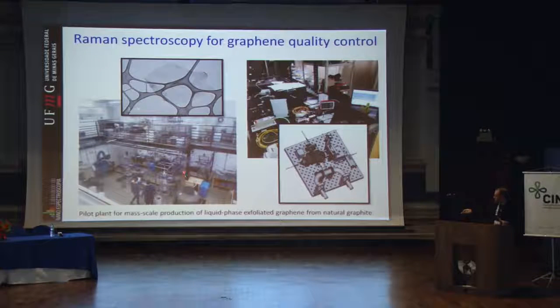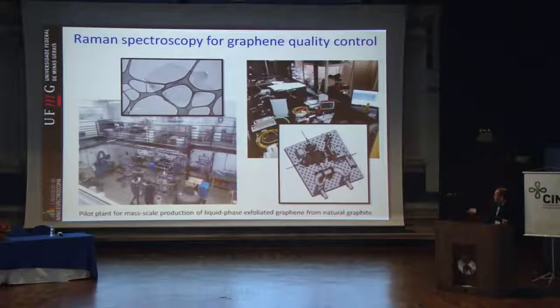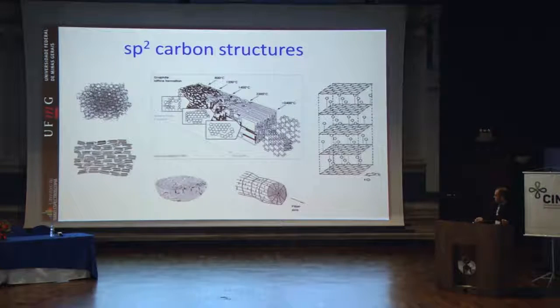is, so they have this pilot plant to produce graphene, and what we are doing is we installed a system that is on the line, because the production is you take the graphite from the mine and you do liquid phase exfoliation. So they have a tube with this material flowing, and we want to measure during the production the Raman spectrum that will tell the number of layers, that will tell in control in real time the number of layers that they produce in these liquid exfoliation machines. Okay, so we built this project for the graphene state company.